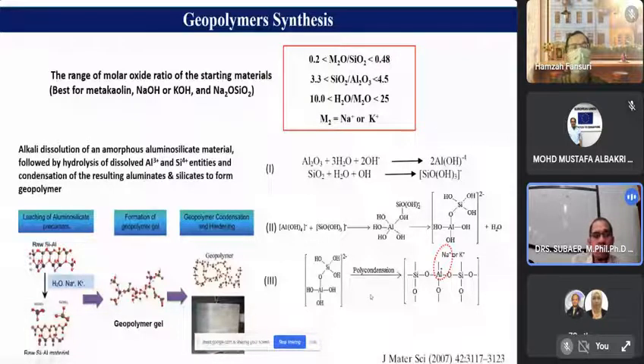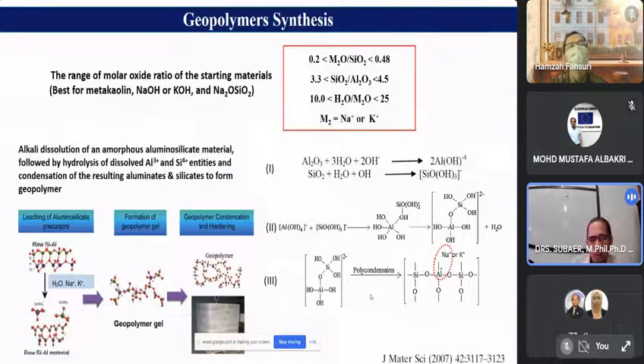And then we will start the polycondensation by a simple manual mix, around 5 minutes at least if your volume of material is not too high, then with the help of temperature below 100 degrees Celsius, you should be able to produce a solid material called geopolymer. So it's quite simple in the synthesis of geopolymer, although it doesn't always produce a good result because there are still a lot of parameters that you need to control in order to produce a good geopolymer. So theoretically, probably you can follow quite well, but